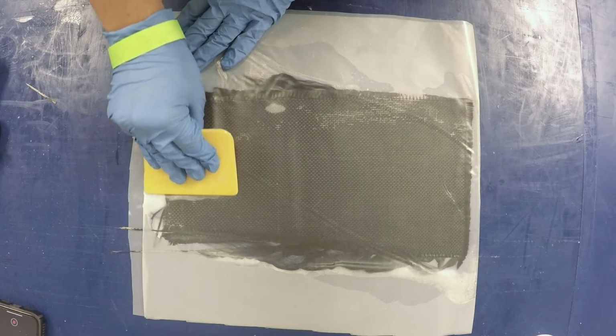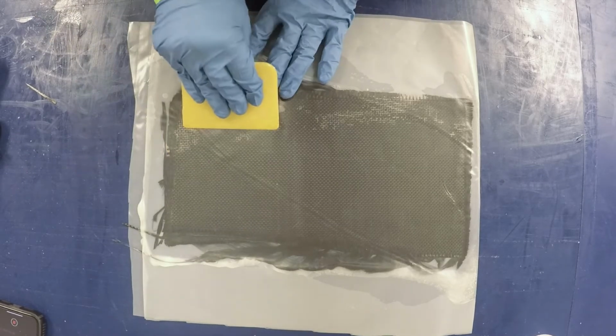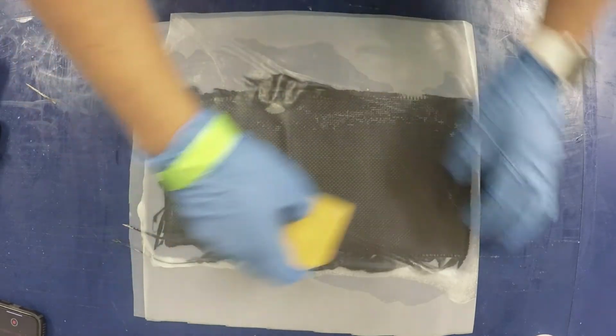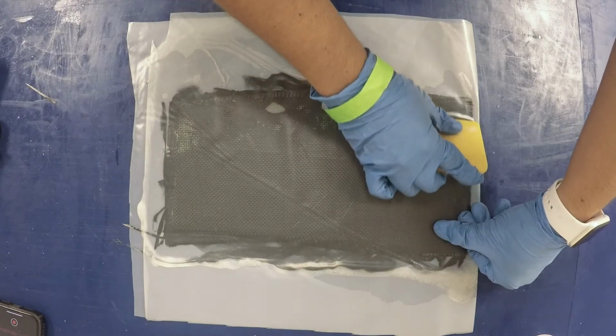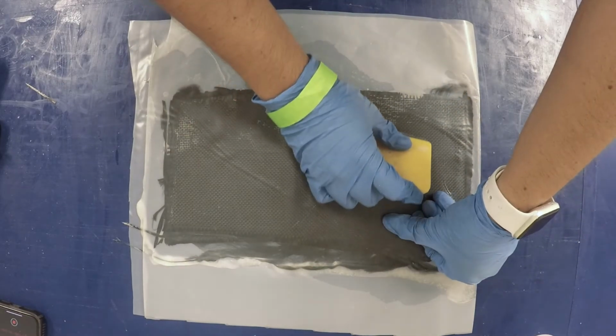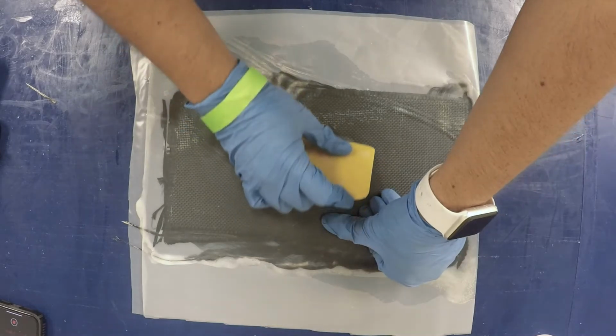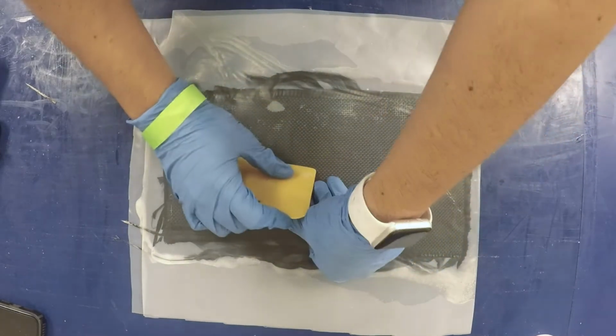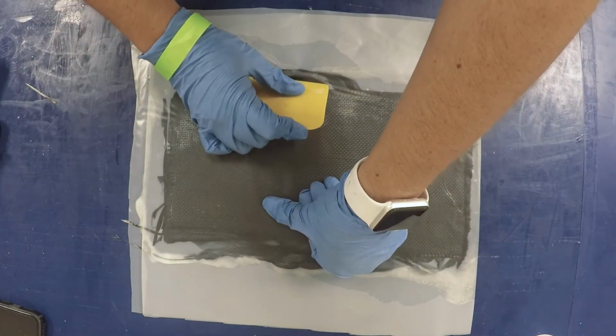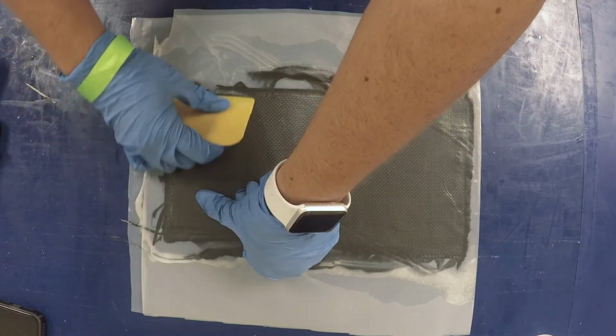Having fully wet out both layers of fabrics, you can push all of your extra epoxy out of the way with a squeegee by using a little more force than you were using before. Not only does this remove any extra epoxy and produce a lighter product, it also aids in removing any trapped air bubbles from within the fibers.